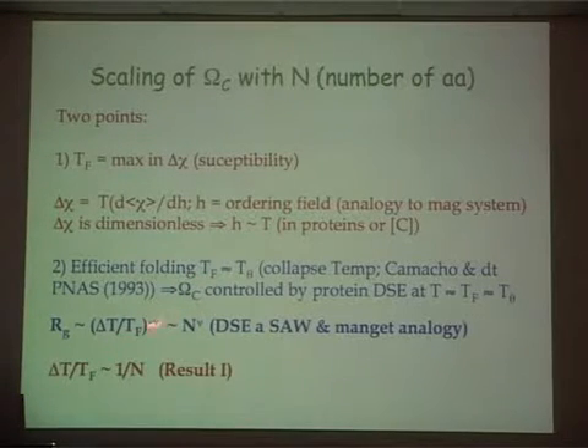We know from de Gennes's work that the RG near this collapse temperature must go as the width of this transition that I showed you in the previous graphs, divided by the temperature, to this exponent nu, and we already met nu before, that's a Flory exponent. So RG must go as n to the nu, which implies that the width of the transition divided by the melting temperature must go as 1 over n. This, of course, is a thermodynamic statement that the transition becomes sharper and sharper as n increases, and this is really a finite size correction, if you wish, to the melting.